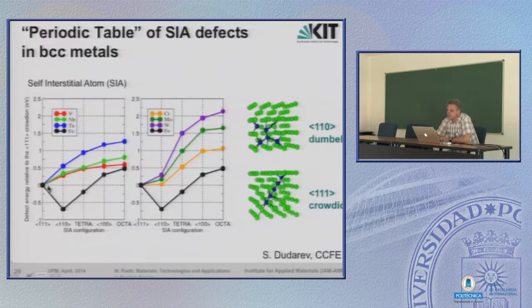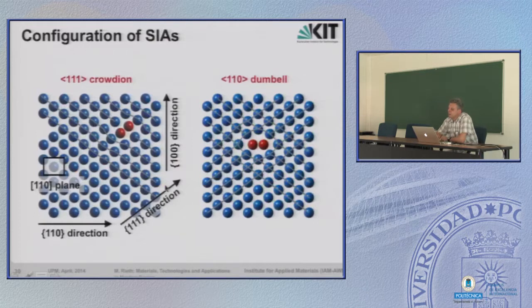So in iron, not the 1-1-1, but the 1-1-0 dumbbell configuration is how self-interstitial atoms are formed. Here, if we compare it with chromium, molybdenum, and tungsten, you see in tungsten and molybdenum also the 1-1-1 crowdion is most stable. For iron, again, the 1-1-0. But for chromium, there is almost no difference between dumbbell and crowdion. So in a chromium lattice, probably there are both varieties almost equally distributed. But in iron, we have to deal with a dumbbell.